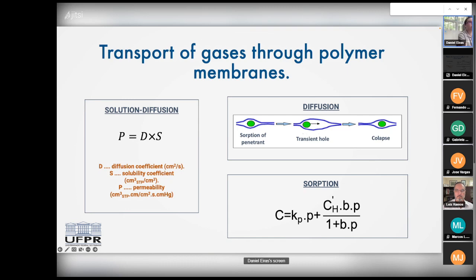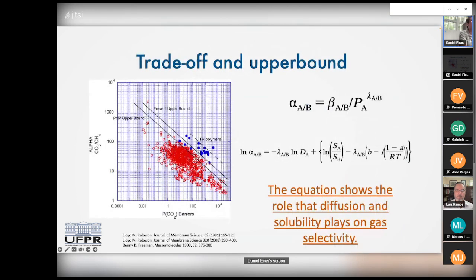So what happens when we modify the polymer membrane is that we change either the diffusion coefficient or the sorption coefficient, or both, depending on the situation. One way to understand that is to analyze the relationship between the selectivity, that is the alpha parameter in this first equation, and the permeability, that is the PA in the same equation. There is a direct relationship between the selectivity and the permeability that we call the trade-off. So there is a compromise between these two properties: when we increase the permeability, we decrease the selectivity. If we increase the selectivity, we decrease the permeability. And that's very unfortunate because what we want is to increase both at the same time.